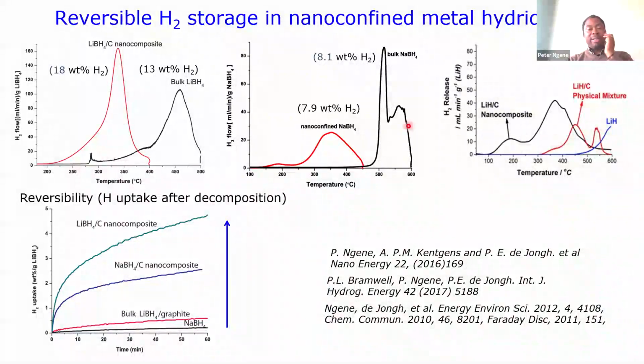And what about reversibility? What do I mean by reversibility? The ability to take up hydrogen after you have decomposed the material. We do see that if you have bulk sodium borohydride and you don't do anything, after it decomposes, you heat it up under hydrogen pressure. You want to monitor how much hydrogen is absorbed, in this case by reaction to make the hydride. And then you can see that the sodium borohydride doesn't work. The same is true for lithium borohydride, even when they are supported on just pure graphite.